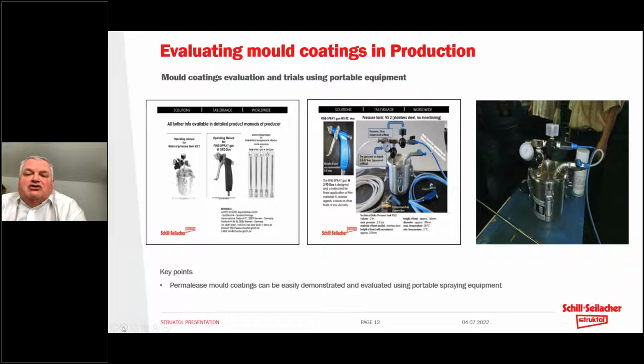And as part of the service that you would get from any good mold release supplier, they would also recommend, of course, the correct mold application methods and provide maybe links or even availability for the equipment. And in fact, what we do with our customers and our distribution partners is to provide a portable self-contained system that you see in the photograph on the right that allows us to completely separate our trial product, if you like, from the product that's in use.